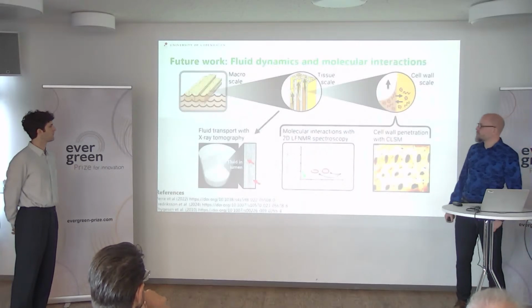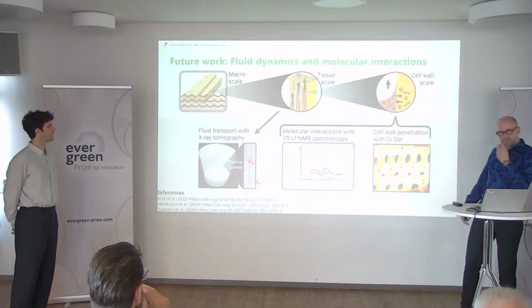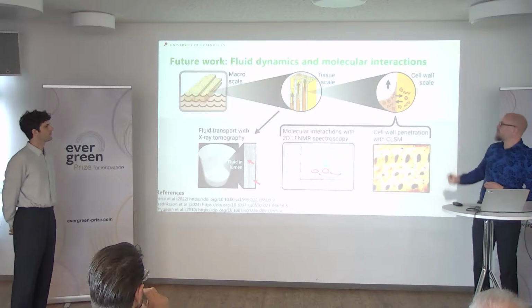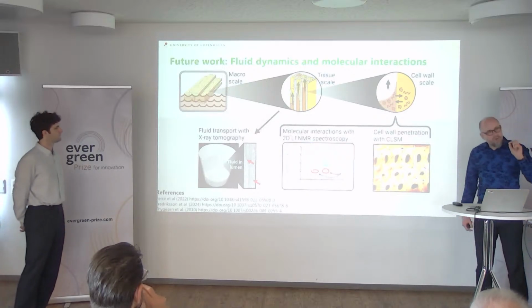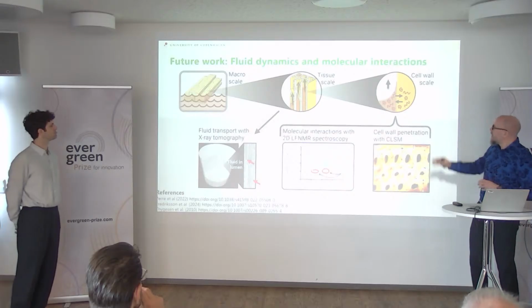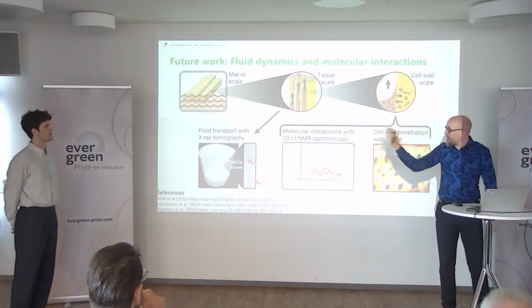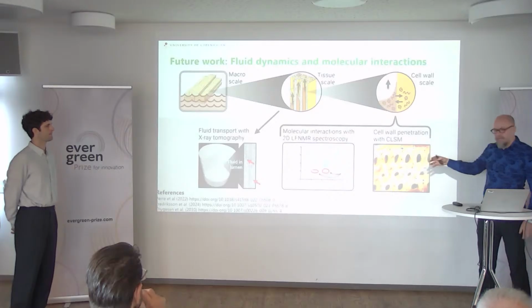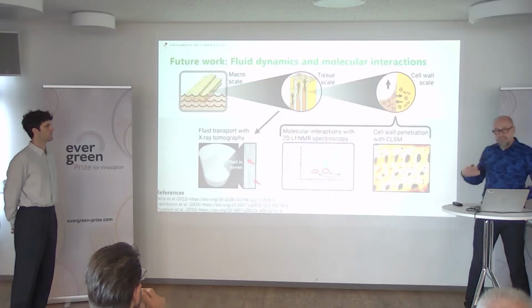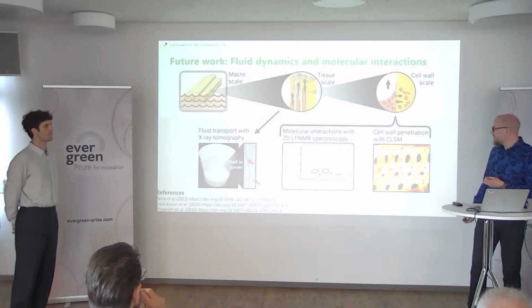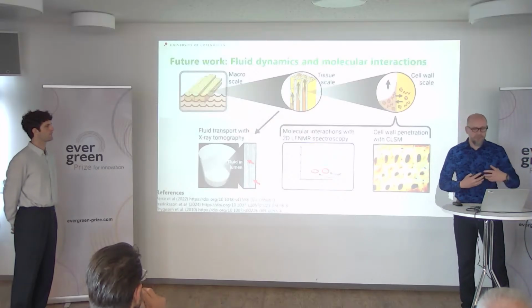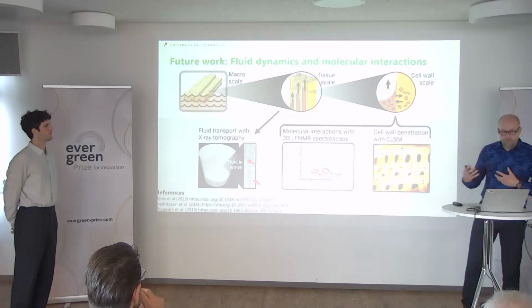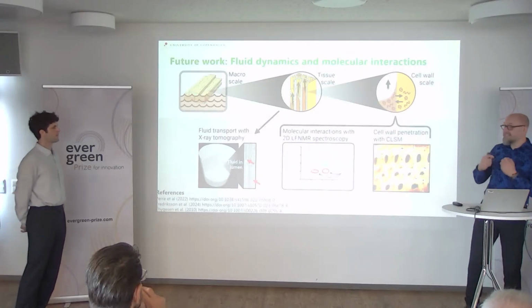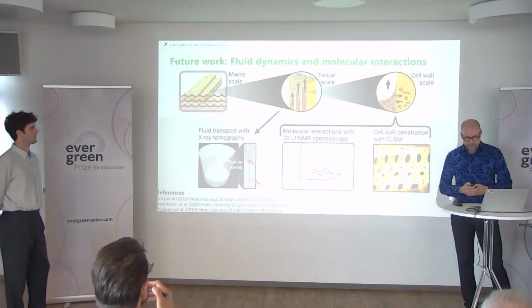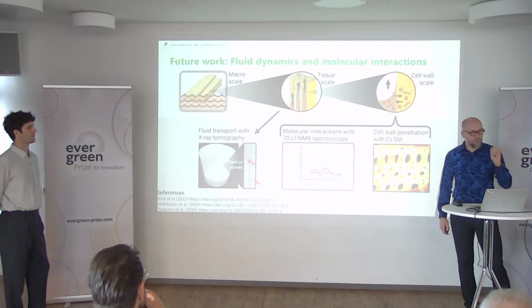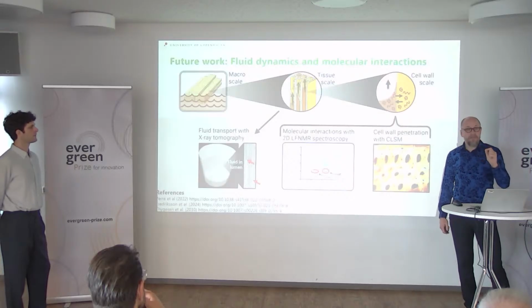We want to go further down this route and study how more well-defined fractionated lignin solutions are transported in the wood structure and how lignin molecules are migrating into the cell walls. With regards to the fluid transport, we plan to use X-ray tomography. When it comes to seeing this penetration of cell walls, we are using confocal laser scanning microscopy or similar techniques. And for this interaction, we want to use spectroscopic techniques like low-field NMR to see how the fluid and the cell wall interact. Basically, we want to better understand how these solutions behave in order to make hyperlignification work even better.